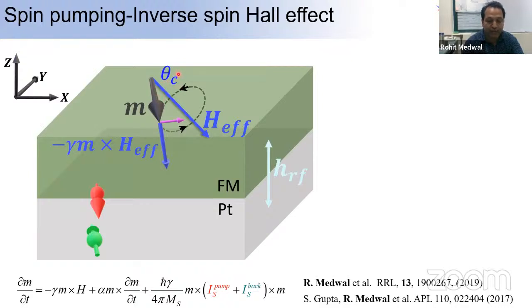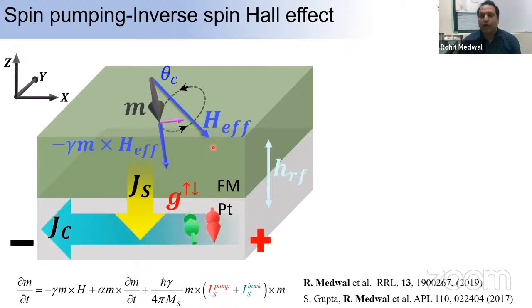This precession cone angle is also an important factor when we are trying to discover spin Hall materials. So the magnetization is precessing about the effective magnetic field, and this precessing magnet will allow the spins to pump into the platinum. This is a source of spin current, which will inject the spins into the platinum.